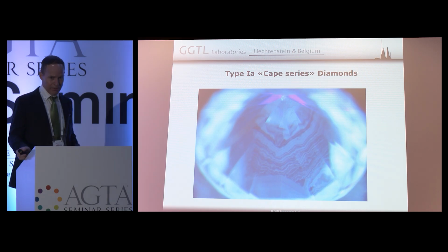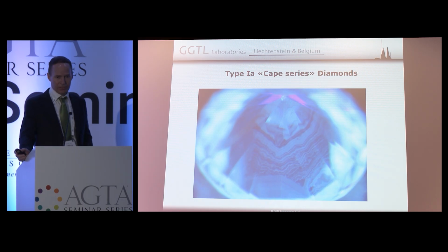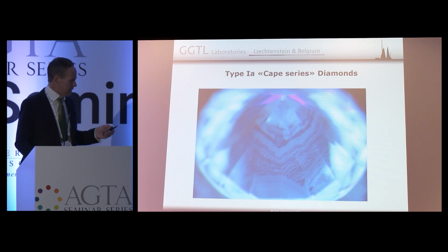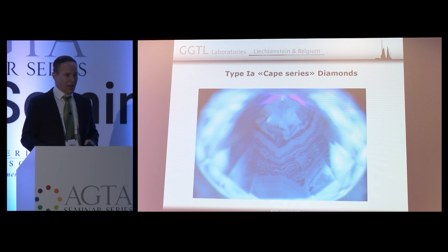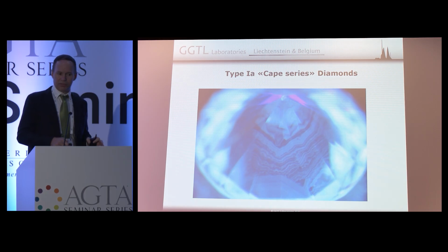The most common ones, Cape series diamonds. So if you have a Cape diamond, just a D to Z regular Cape diamond, this is a typical kind of reaction you will see under deep UV. So this is deep UV excitation. What we're seeing here are cuboid and octahedral growth sectors. Cuboid growth is common in diamond. It's more common in some than in others. In Cape stones, it's not very, very common.